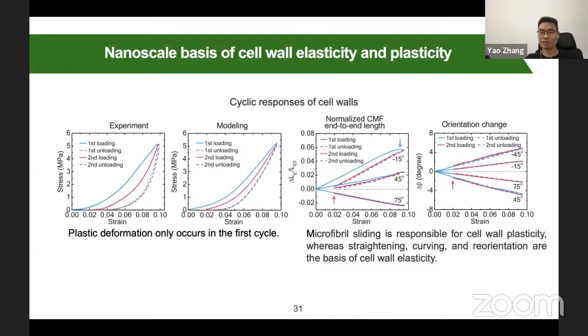In the second cycle and in the third cycle, as long as you keep the maximal strain the same, it will not have this plastic deformation. So what we found is that this microfibril sliding is responsible for cell wall plasticity. And if you look at the second cycle or third cycle, the microfibril end-to-end length is just recoverable.